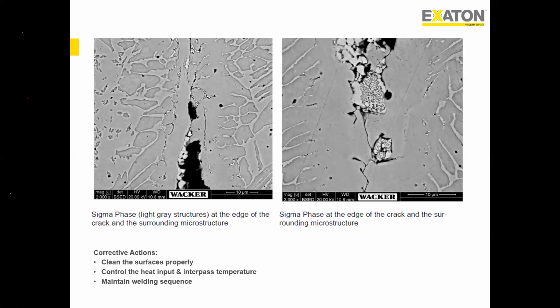So we recommend to clean the bevel properly with the acetone. There was a lot of undesired grease, cutting marks, and some sulfur content. When they started welding, it got burned, and when it got burned, it tried to absorb the moisture and sulfur. So cleaning was very important. And because they did a submerged process, when they start the welding, because of the high thickness, it has a very high cooling rate.